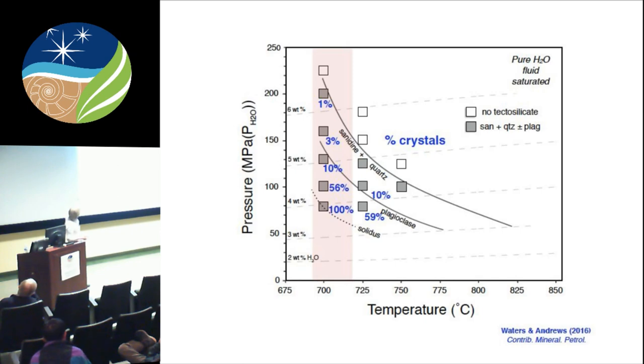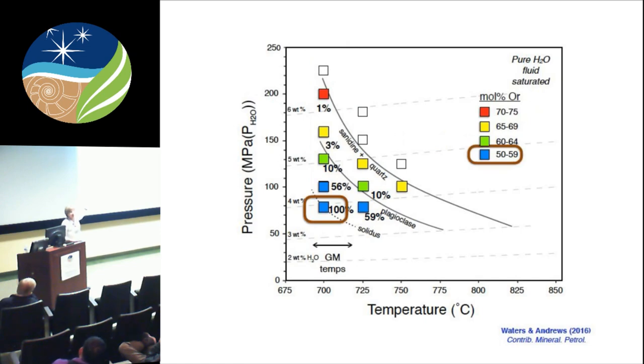The other important thing is the crystallinity. Plag seems to come in at around 10% plag crystallinity. And then once plag is present, boom, you immediately end up half the rock crystallized and then hit the solidus very quickly. So this is where the eutectic behavior really is kicking in. The other important point is the composition of the orthoclase appears to vary strongly with water content, in the same way that plagioclase seems to vary with water content.